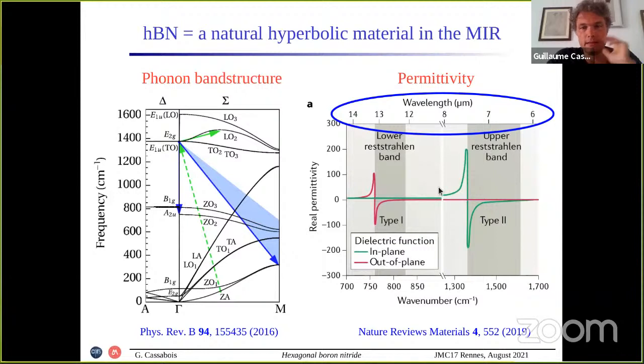This is the reason why we have hyperbolicity in hexagonal boron nitride. If the material were isotropic, these modes would be degenerate, this Reststrahlen band would superpose on this one, and there would be no hyperbolicity. Because of the anisotropy, we have this decoupling of the two Reststrahlen bands.